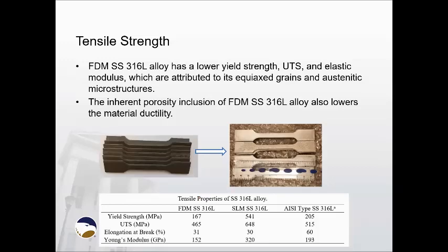Now for the tensile test, the flat bar is directly printed using the 3D printer, and then it is sent out for debinding and sintering. And I use an Instron tensile tester for the tensile test. So the yield strength, UTS, and elastic modulus are evaluated using this test. It seems like the yield strength is much lower than the SLM stainless steel, but it has a comparable elongation. The strain is about 30%. The UTS is about